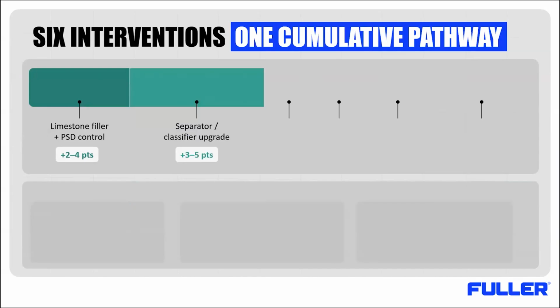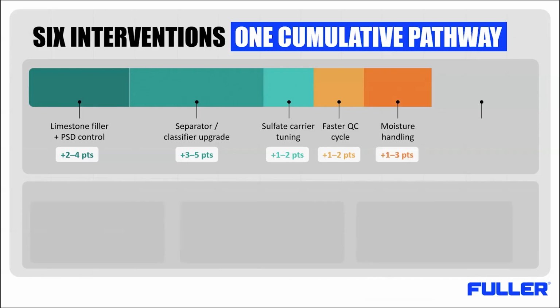A separator or classifier upgrade can add another 3 to 5 percentage points if the classification is the real bottleneck. Sulfate tuning and faster quality control may each support 1 to 2 percentage points. Moisture handling may unlock 1 to 3 percentage points, especially with wet SCMs. Finally, SCM blend optimization may add another 2 to 4 percentage points of clinker reduction.